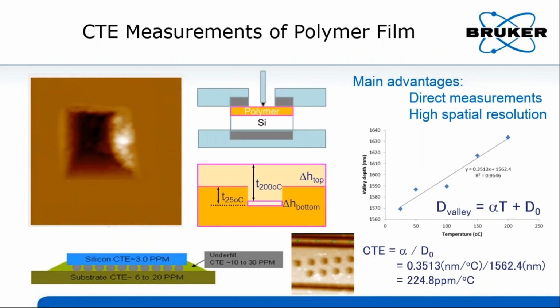This is the slide showing an example of this method. The sample is a polymer film with a thickness of 5 micron used as underfill. Firstly, a worn region was created at room temperature, and the depth is around 1.5, 1.6 micron at the beginning. And then the in situ SPM was performed at different temperature levels from room temperature up to 200 degrees Celsius, which is slightly below its Tg.